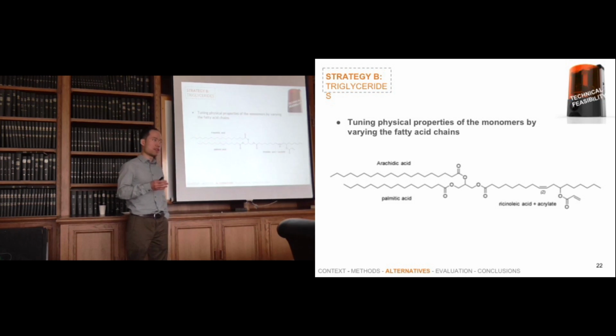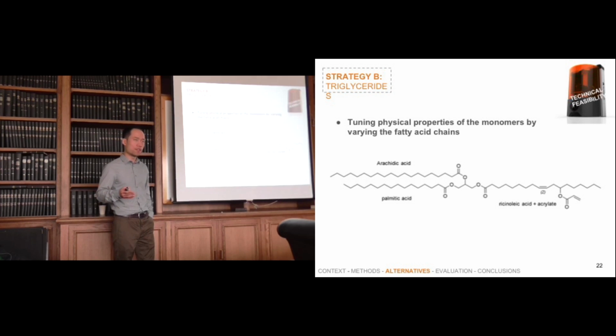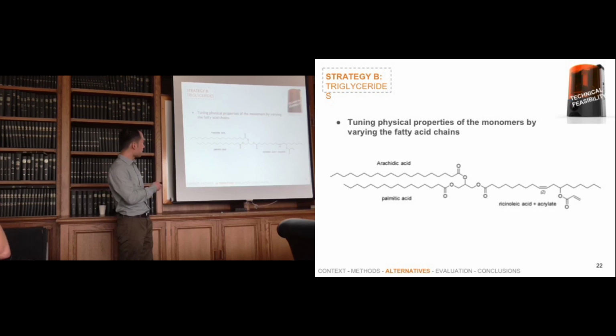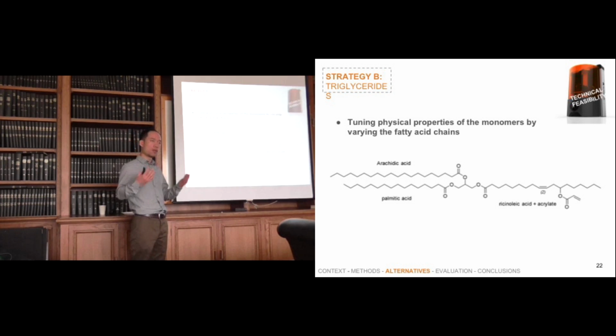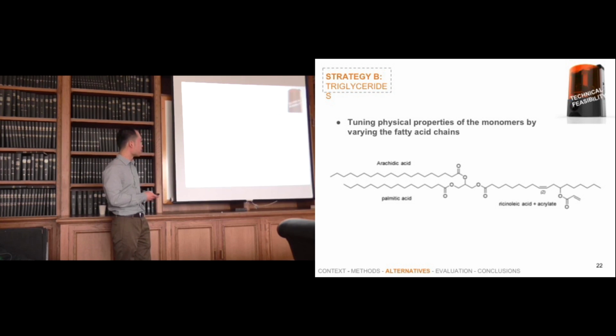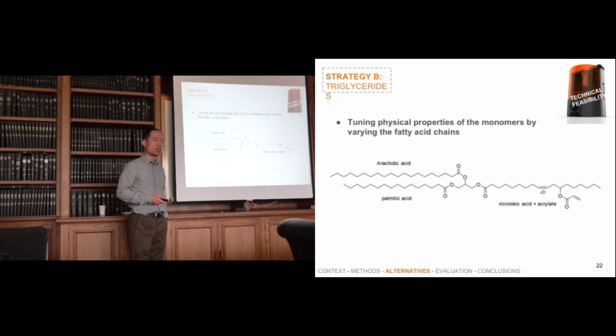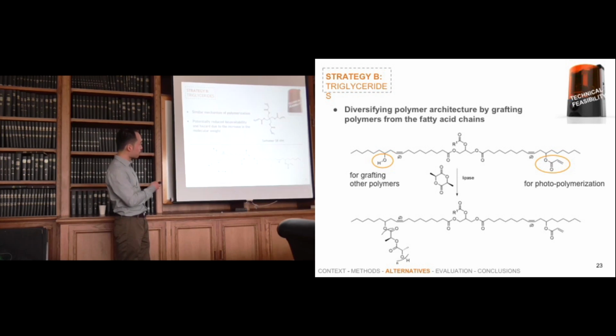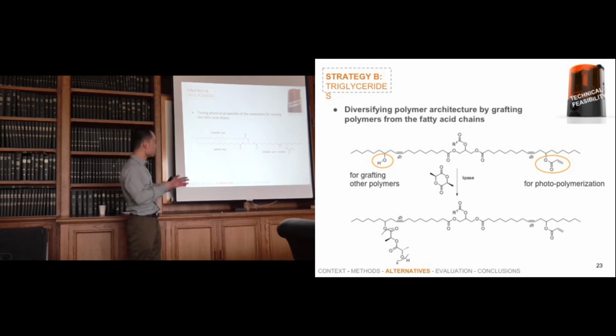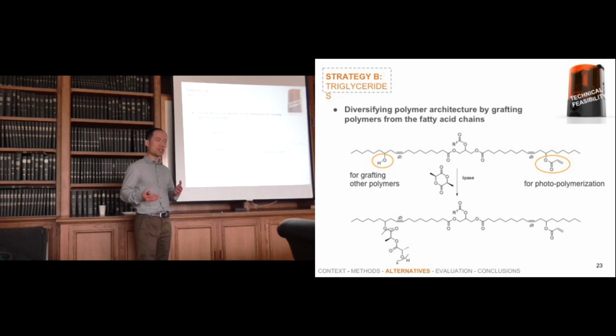As I mentioned previously, we have a wide range of different naturally occurring fatty acids, and we can swap those side chains to an arbitrary fatty acid chain to fine-tune the mechanical and physical properties of the monomer. So if you look at this molecule, it has 1 acrylate per monomer, and comparing that to the previous slide where we have 3 acrylates per monomer, those 2 molecules should produce 2 polymers with very different degrees of cross-linking and different mechanical and physical strengths.